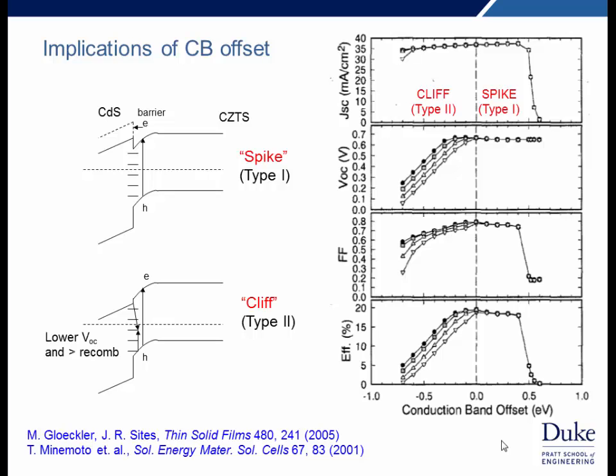If we have a spike and it gets too big, this is going to act as a barrier to current transfer or current flow, and it's going to lead to a reduction in the short circuit current, which will ultimately end up hurting the efficiency. In the case of a cliff, the cliff will enhance recombination at this interface and hurt the open circuit voltage, which again will show up in the efficiency. And so ideally we'd like to have a very small barrier or spike at the interface between CZTS and CdS, somewhere in the range of 0 to 0.4 eV.